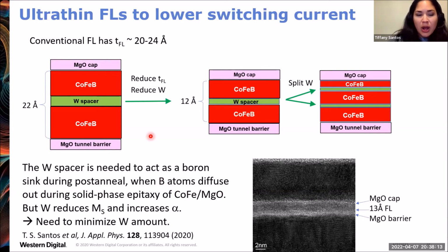Otherwise, the tungsten there acts to reduce the saturation magnetization and increase the damping parameter. So we want to minimize as much as possible how much tungsten we put in there as the boron sink. Our strategy for doing this is to overall reduce the thickness of the free layer. That allows us to reduce the tungsten spacer thickness substantially, yet still maintain perpendicular magnetic anisotropy. For example, here the free layer thickness is reduced down to 12 angstroms. And we found that the properties improve even more if we take this single tungsten spacer and split it into two even thinner spacers, yet maintaining the same total 12 angstrom thickness.